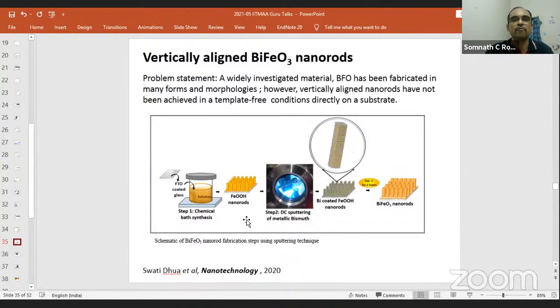We took first simple iron hydroxide, FeOH solution. Sorry, we started with iron chloride solution. We just immersed glass, specially conductive glass, FTO coated glass. When we do that, we don't have to do anything. It is not our work. This part was already reported, where you can see vertically aligned FeOOH nanorods beautifully grow. This is a metastable structure.